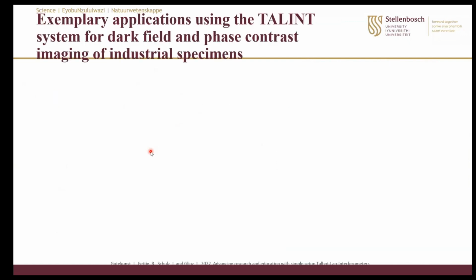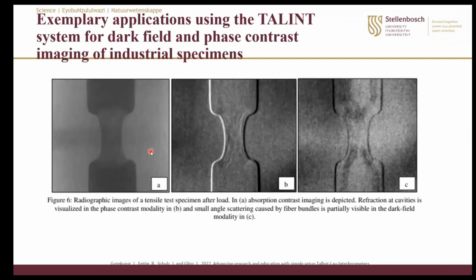Because I have not yet scanned my sample with the phase contrast system, I've just taken out some images that give a brief demonstration of how my results will look after I've scanned the samples. This is a tensile sample that was also used in the paper as a test sample to demonstrate how the system works. On the first image, the absorption contrast image, by the notch of the sample, there is low absorption, which is caused by a reduction of the cross section.